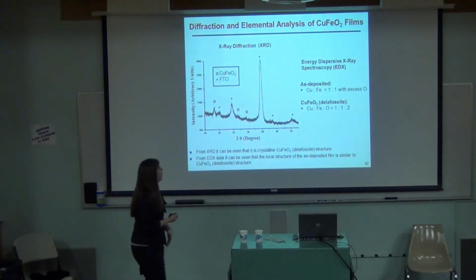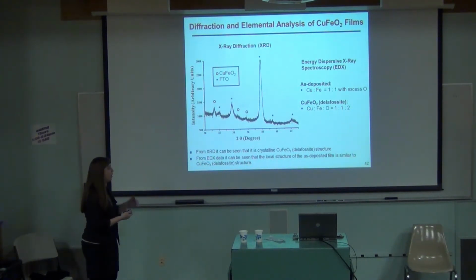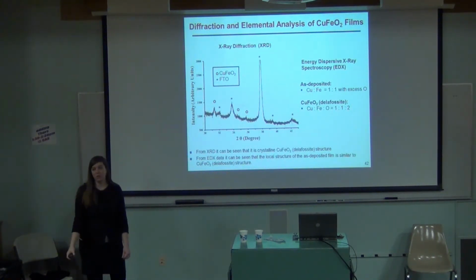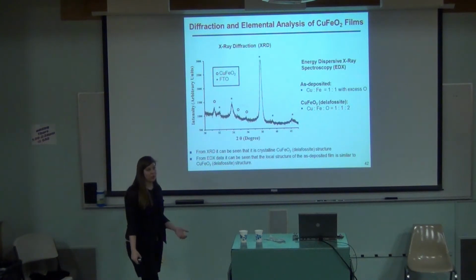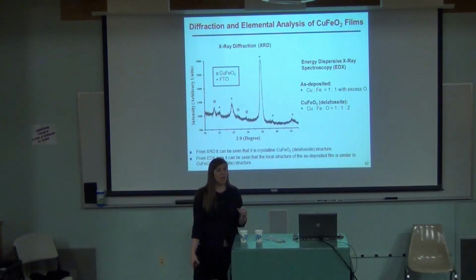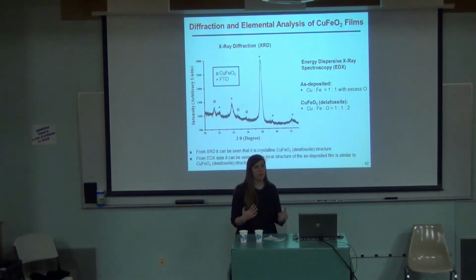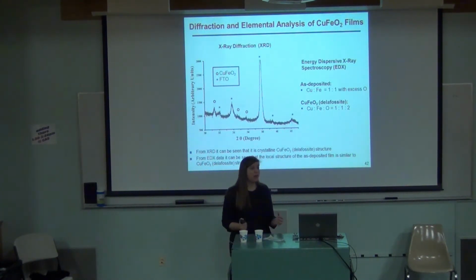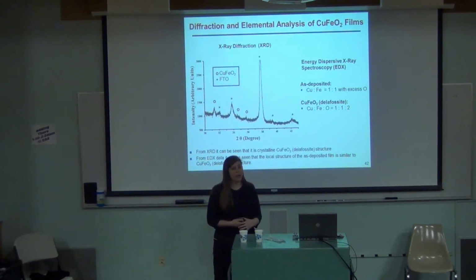So we proved that by showing the EDX spectra was a 1-to-1 instead of the other ratio that we were using, and after my annealing, you can see these very small, not very sharp peaks of copper iron oxide. So this is where improvement needs to happen. Even though I did deposit a Delafossite structure, it wasn't crystalline as deposited, and it's not even that crystalline once you anneal it. This was towards the end, I was trying to write my thesis and graduate and find a job and leave, so I didn't get to focus as much attention on this, but I think there's room for improvement on making this a better material, or finding another material that you can electrodeposit that might not have these same properties.